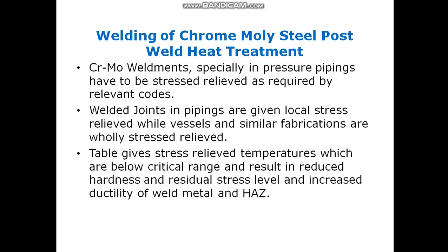Now, welding of Cr-Mo steel: post-weld heat treatment. Cr-Mo steels, especially in pressure piping, have to be stress relieved as required by the relevant codes. Depending on the size and geometry, these welded joints are either locally stress relieved or sometimes wholly stress relieved in a furnace. They are locally stress relieved by means of a thermal jacket.